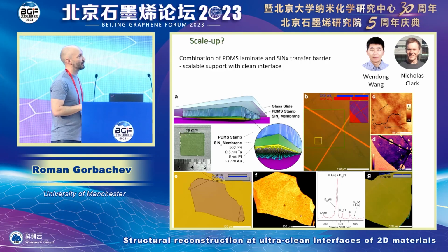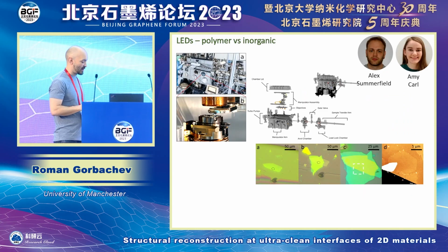materials. And one example we've made here is a tungsten sulfide monolayer on a few-layer tungsten sulfide grown on sapphire. This is a millimeter-scale sample. We are trying to scale this up at the moment, but this is work in progress. A lot really depends on the supply of 2D materials, and if you can find really nice monocrystalline uniform monolayers of TMDs, it's a lot easier to make this technology happen compared to the normal state-of-the-art